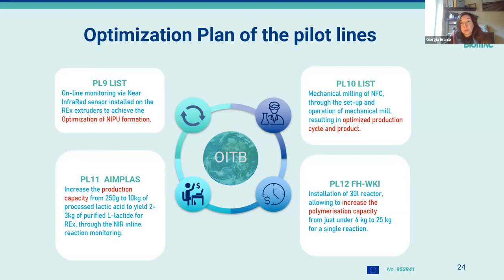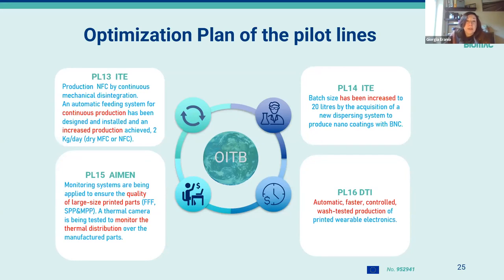The pilot line 12 by Fraunhofer managed to install a 30-liter reactor, allowing the increase of polymerization capacity from just under 4 kg to 25 kg for a single reaction. Pilot line 13 managed to produce NFC by a continuous mechanical disintegration. An automatic feeding system for continuous production has been designed and installed, and increased production achieved up to 2 kg per day of dry MFC or NFC.